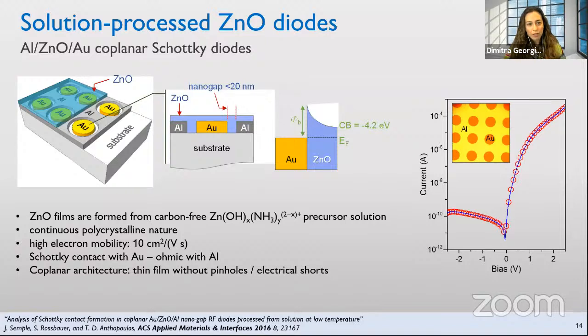This is because the barrier height between gold and the conduction band of zinc oxide is quite high. And again, this is a coplanar structure, so we managed to have films which are very thin, but they have no pinholes, so no electrical shorts are happening. You can see here a representative IV of this diode, which shows a quite high rectification ratio and a low reverse current. It shows first that the electrodes are not shorted if we apply voltage between aluminum and gold. Second, we can see that there is a material, because if no material was in the gap, we would get very low current constantly as we would increase the voltage, while in this case we are quite certain that this performance is due to the material we have used.